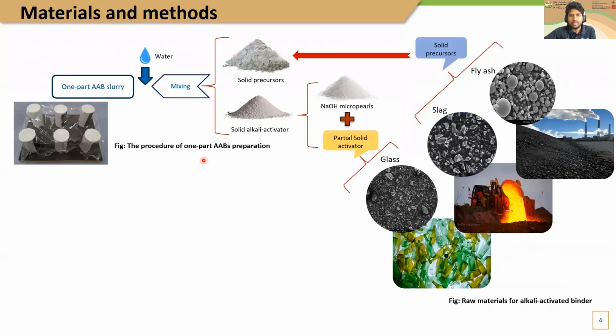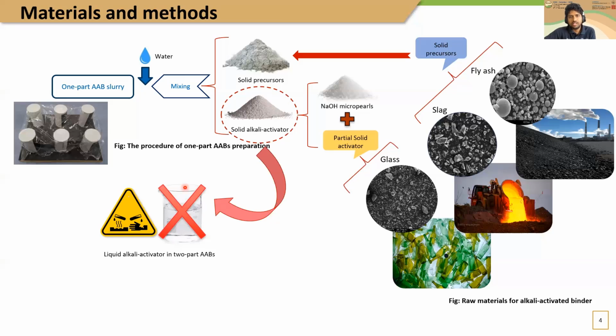If you consider the waste glass based solid activator powder, our final objective is to prepare sodium silicate, which is a better alkali activator in fly ash slag cement binders. Here, waste glass acts as a silica supplier, and sodium hydroxide acts as the main alkali source to form sodium silicate. In the case of using waste glass as an alkali activator, it was prepared in solid form rather than using liquid and corrosive alkali solutions such as sodium hydroxide or sodium silicates. Therefore, it is called one-part alkali-activated binders, and they have several advantages in handling and mixing at in-situ conditions compared to two-part alkali-activated binders, which use liquid alkali activators.